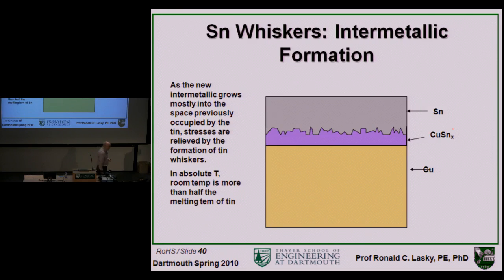And one of the mechanisms that makes it worse is, so you have some sort of a lead that's copper and you want to put tin on it. And when you do that, you get a copper-tin intermetallic at the interface between the tin and the copper. But one of the problems is that in absolute sense, the room temperature is more than 50% of the melting temperature of tin. And so at room temperature, tin is still quite active. And once you put this coating on and leave it even at room temperature, the intermetallics continue to slowly form, but it's one directional for the most part.